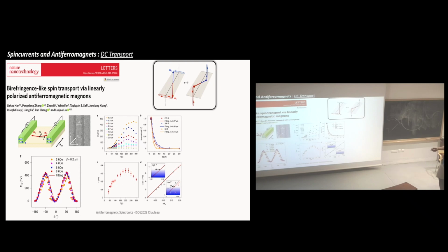You have to remember that in this kind of system you have two linearly polarized modes. If you try to inject some angular momentum, some ħ, with the two linearly polarized modes, then they will try to match the dispersion relation of your material, and they are separated by some value. Because it is injected at the same frequency, it will be at different k vectors. Since they have different k vectors, at the beginning you have the ħ, but then they will dephase, and at the end you will end up with no more spin information. This dephasing will depend on how far apart those two branches are.